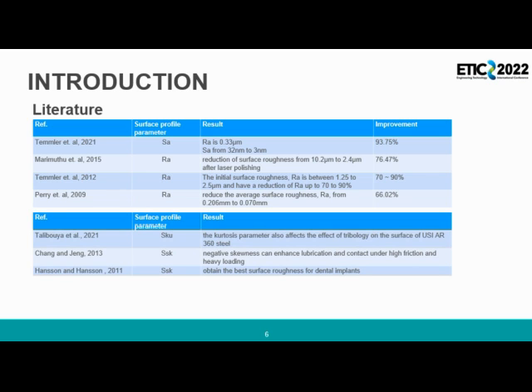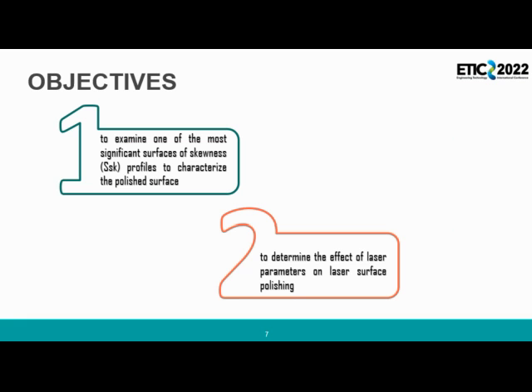There are several previous studies on the effect of skewness on certain applications. Chang and Jeng demonstrated negative skewness can enhance lubrication and contact under high friction and heavy loading. Similar results were achieved in a study conducted by Talibouya, where the kurtosis parameter also affects the tribology of the surface. Hansson and Hansson used the skewness parameter to obtain the surface roughness for dental implants.